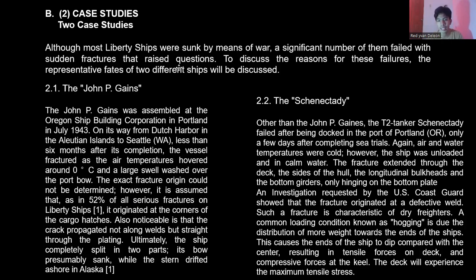Number two, the Schenectady. Other than the John P. Gaines, the T2 tanker Schenectady failed after being docked in Portland, only a few days after completing trials, while air and water temperatures were cold. However, the ship was unloaded and in calm water. The fracture extended through the deck, the side of the hull, and the longitudinal bulkheads, and bottom girders, hinging only on the bottom plate.